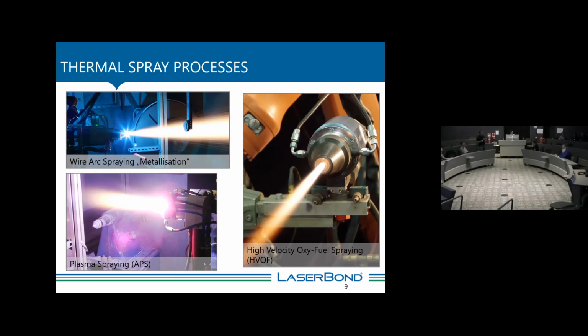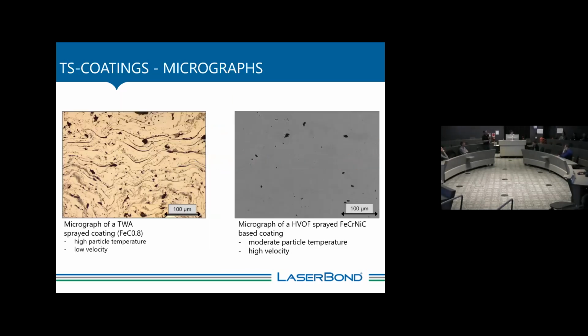The other system can measure these different parameters, and the material as well as the kinetic energy have a tremendous influence on the products. So on the left hand side is the arc spray coating. After melting, the part stays relatively cool, and we try to keep the surface temperature below 200 degrees C. As I mentioned, you see the lamellas or splats here, the grayish ones, some porosity, some oxide stringers, but it's a very reliable process.